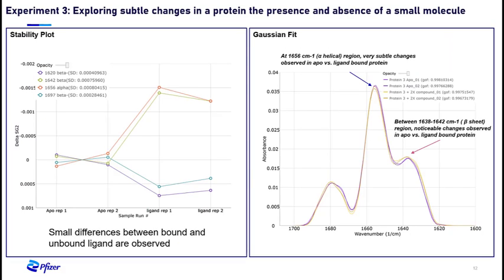In this next slide from experiment 3, we can show additional data. On the left is a stability plot. And again, from this plot, we can see that there are small differences between bound and unbound protein. To the right, a Gaussian fit plot shows the very subtle changes observed in the alpha helical region between the two sample sets, and a more obvious change in the beta sheet region between apo and ligand bound. The ligand bound is in yellow. These changes are not huge, but they are detectable.